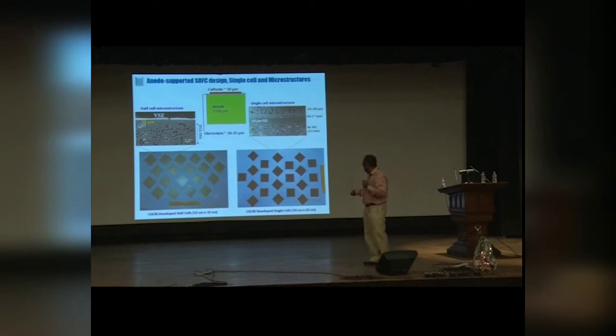So this technology we have made in our institute, and we are producing very big cells, 10 centimeter by 10 centimeter, and there is no porosity. If there is any porosity, then hydrogen will leak from this side to that side, and from the other side oxygen may come. If oxygen and hydrogen mix in this electrolyte, you will not get any voltage, there will be an explosion rather. So that is the reason this has to be fully dense.